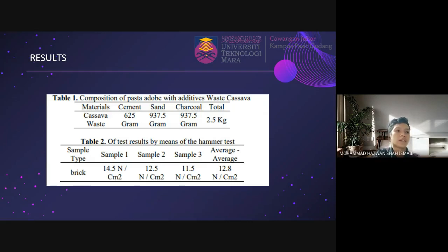Sample 1, the brick from the hammer test gets 14.5 Newton per centimeter square. For sample 2, 12.5 Newton per centimeter square. And for sample 3, 11.5 Newton per centimeter square. The average of all the sample hammer tests is 12.8 Newton per centimeter square.